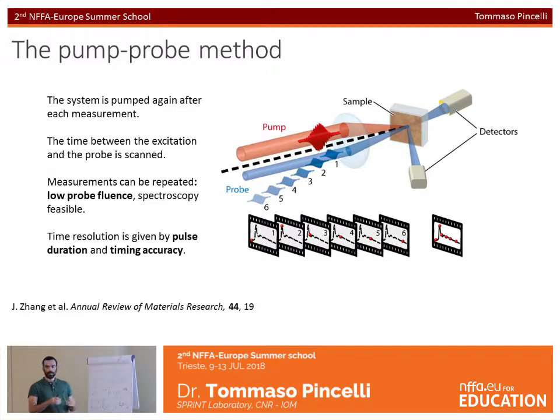Because we can acquire a measurement for as long as we like by staying at this precise delay, we can use a low-intensity probe, so we can perform spectroscopy in a rather simple way. As we will see, if we use single-shot approaches, which will come in a minute, then you will have to use very high intensities, and you will be out of the approximation that your probe is just looking at the system. If you use very high intensity, the probe will also be perturbing the system significantly. So that makes spectroscopy much more complicated.